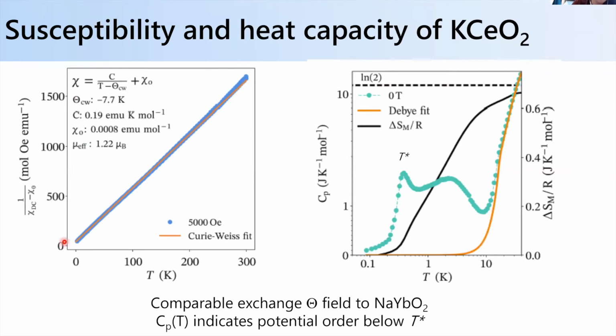So for this system, we can do the same thing. We can do a Curie-Weiss analysis, and again, we can extract a mean field. In this case, the crystal field splitting is larger, so we get a good Curie-Weiss fit all the way up to 300 Kelvin. And so you get a mean field of about -7 Kelvin, antiferromagnetic.